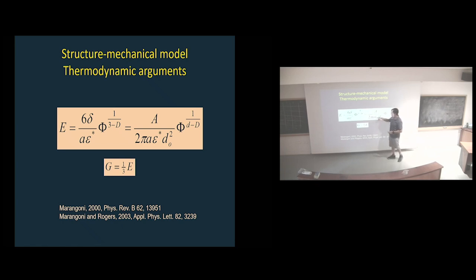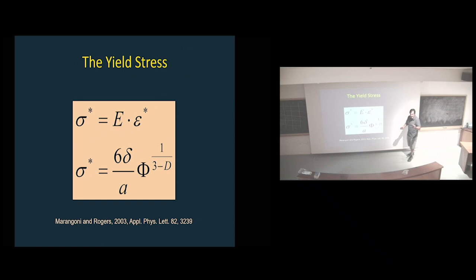But the nice thing is that if you do deformation times a modulus, you end up with a stress, right? And that is the yield stress, and then everything goes away, and you end up with a really simple expression. But this would be a highly idealized system, right? Highly idealized, little spheres and flocs, and everything is close packed, and the world is beautiful. And you have things that you can measure, like particle size and interaction forces via the interfacial tension. You can shove numbers in there and see what numbers you get, and they're not bad at all.